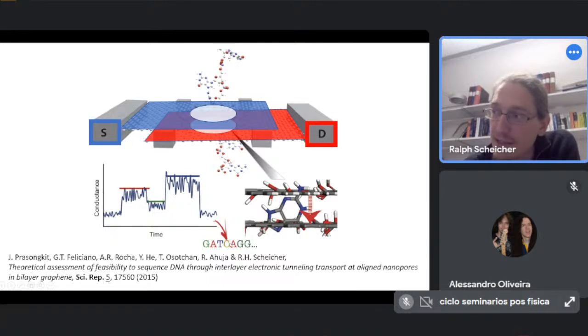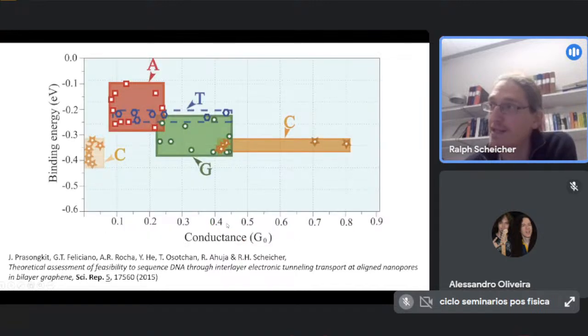And together, then, they can hopefully tell you about the nature of the bases. And indeed, we find that from molecular dynamics simulations and electronic transport calculations here, if we plot the conductance on the horizontal axis and the binding energy of the bases on the vertical axis, then from the MD simulations, taking different snapshots, we have for adenine these red squares, they all fall within a certain region of conductance and binding energy range.